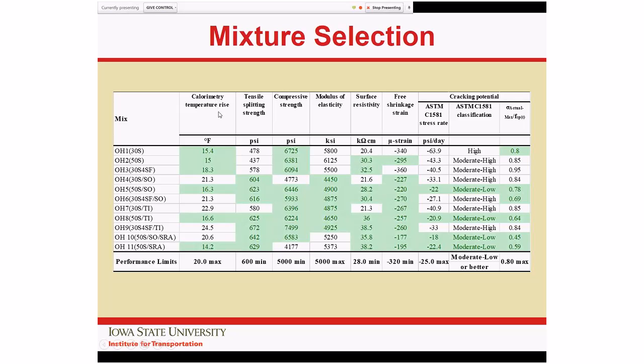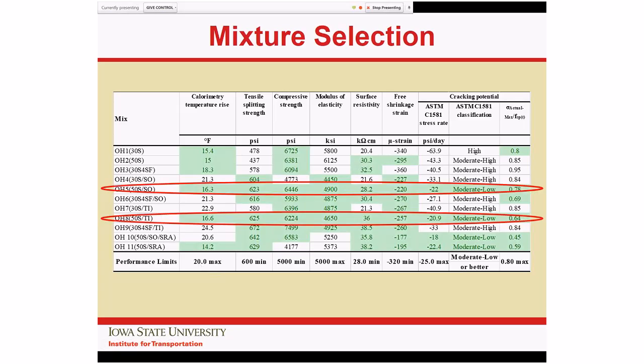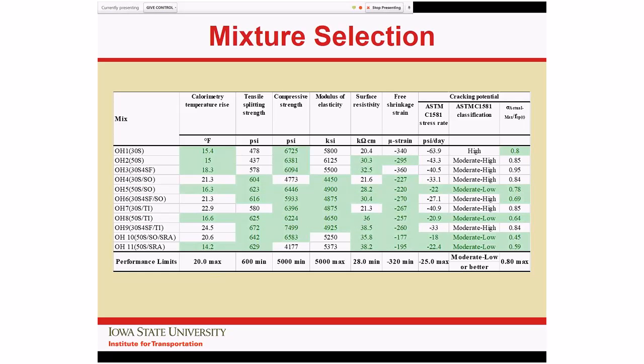So, temperature rise, we used the calorimetry approach. We measured the change in temperature over time and assessed which systems got hottest fastest. And in many ways, the idea being that the higher the temperature rise, the higher the temperature differential, the higher the potential stress in the system. So we imposed, again, an arbitrary 20-degree maximum rise.